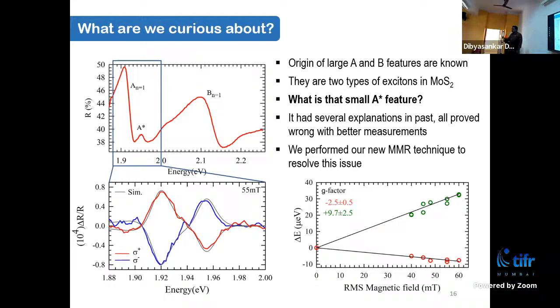But the most interesting thing about this curve is the y-axis. Here I have measured some energy differences of, say, 6 to 7 microelectron volts. In the green, I have measured 20 to 30 microelectron volts. With the technique I described earlier, we could not see anything even at 300 microelectron volts, 10 times that.